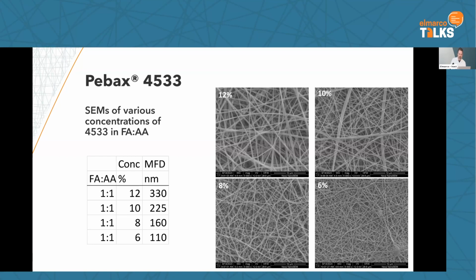We haven't studied everything fully yet, but you can see that there's a nice fiber formation from these materials. And then also the mean fiber diameter range that we've achieved quite easily by just looking at the concentration in a mixture of formic and acetic acid. You can see that this is quite interesting and quite useful to be able to achieve these types of fiber diameters when you're looking at tuning different properties.